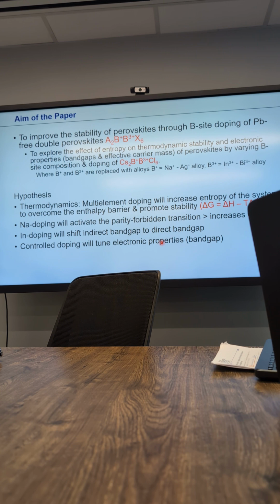And one of the rules they had, I think, at the beginning was that the rule for this double perovskite is the system should have an s2 electronic configuration in the cell, lone pair. And when you have this lone pair in the B3+, you are going to activate that transition. If not, they are all forbidden. Every other material you put there is forbidden.